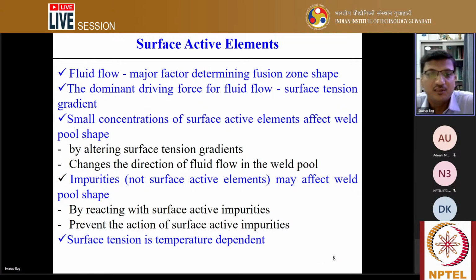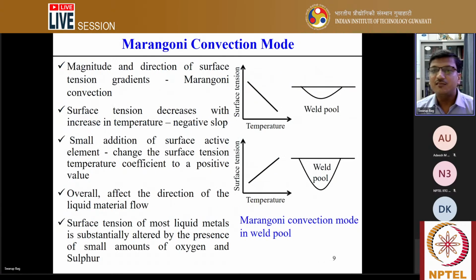Okay, we'll see some examples. That is the main role of the surface active elements, just to change the surface tension gradient. Surface tension gradient changes the flow pattern, and once there is a change in the flow pattern, that actually changes the shape of the fusion zone. Here you can understand in what way the surface tension actually acts. Sometimes it is called the Marangoni convection also. First, the magnitude and the direction of the surface tension gradients are associated with the Marangoni convection, the convective flow of the liquid molten pool from one side to another. The first case is if you see a negative surface tension gradient.